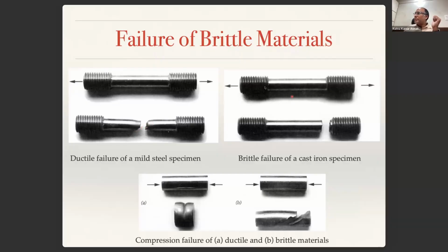And now coming to the brittle material, when you are applying the load, brittle materials will not have any plastic deformation. So that means there is no shear effect. Brittle materials fail by fracture, and as a result, they are limited by their normal strength. That is why if you take a chalk piece, which is a brittle material, and apply a load axially, it breaks normal to the surface, as you can see here. It may break at any point depending upon, here probably because of the stress concentration it broke here. The idea is that it is breaking normal to the surface.